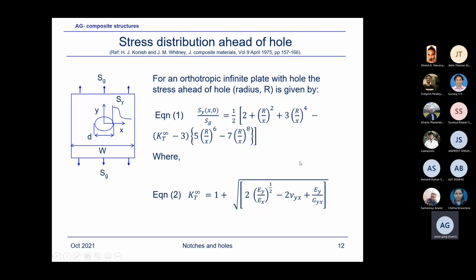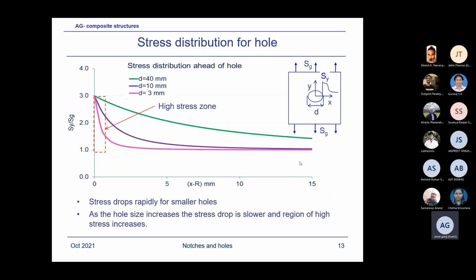So this is just an expression. We need this expression in order to derive our residual strength criteria. This graph is only showing the effect, plotting the stress distribution, which I showed in the previous slide, as a function of the diameter or the radius of the hole and position along the X for the stress.